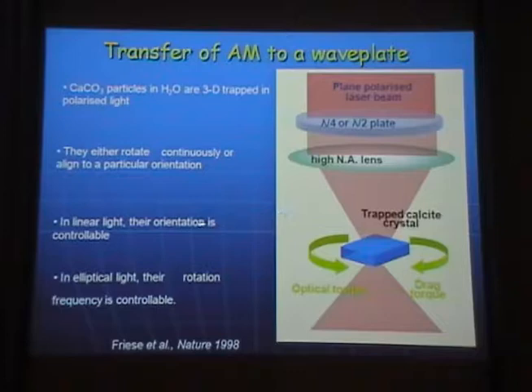So if I have linearly polarized light, and I take a lambda over 2 plate and put it in this position, then the orientation can be controlled. Why? Because I can change the axis of the lambda over 2 plate and the crystal will follow the orientation of the lambda over 2 plate. So if I put this lambda over 2 plate on a motor of some sort, then I can get rotation going. If I have elliptically or circularly polarized light, the crystals will rotate and the frequency of the rotation will be controlled. Okay. So let us look at that.